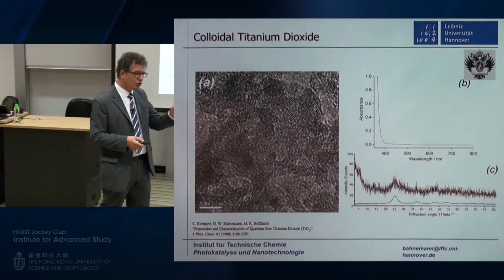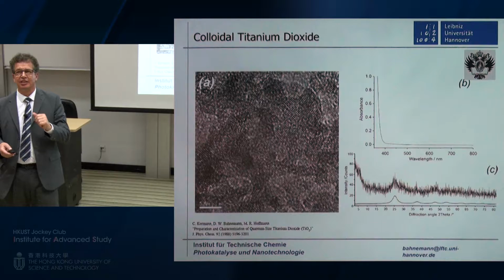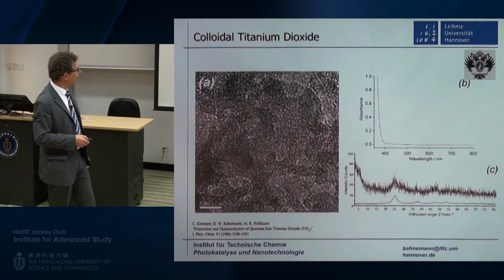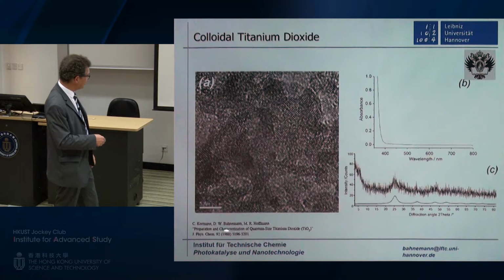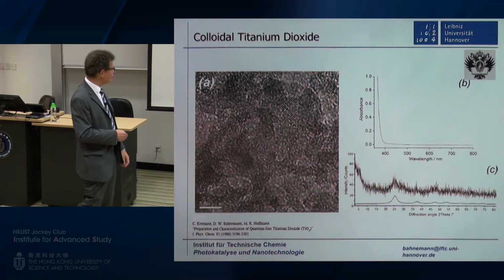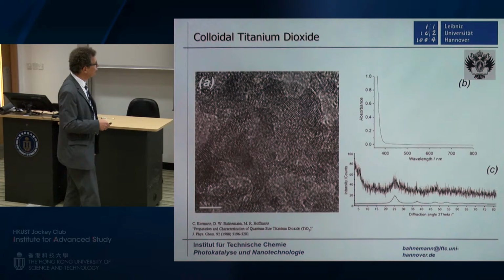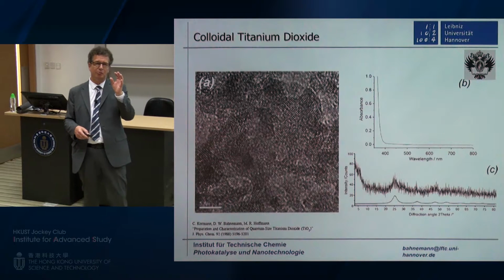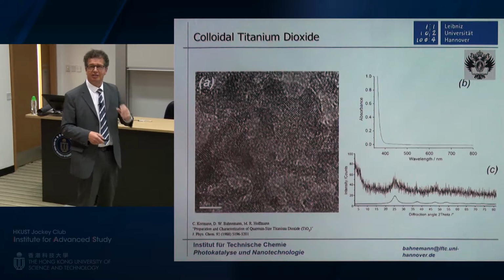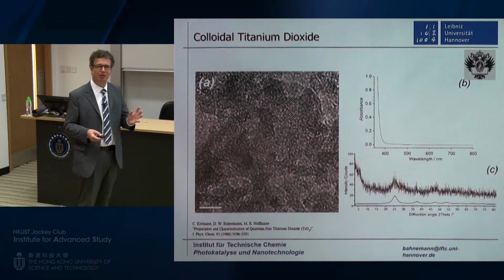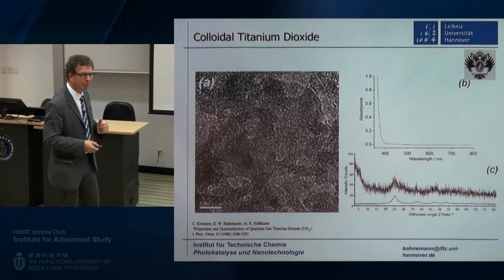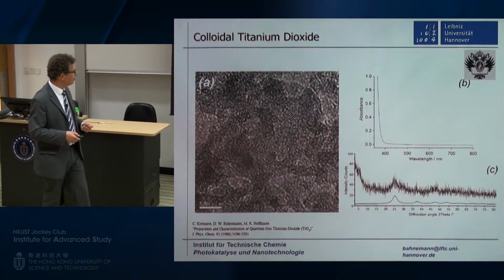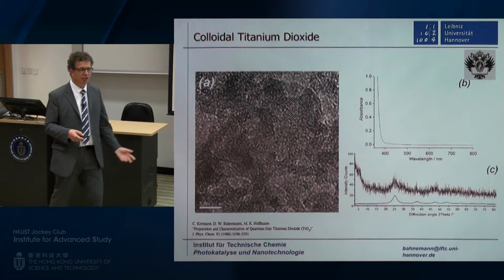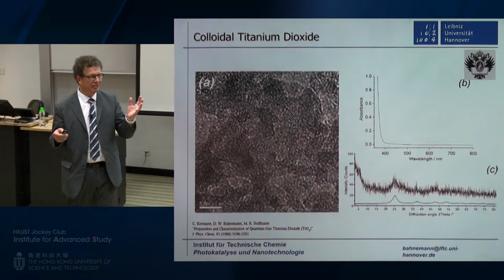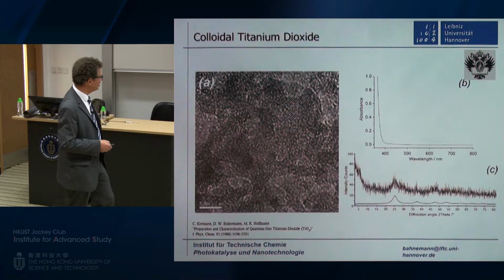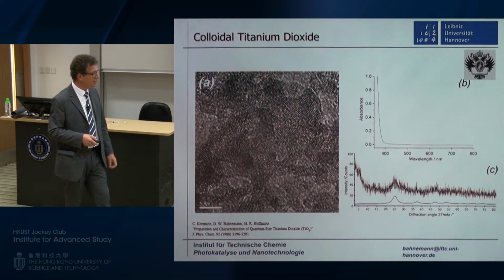Now let's switch gears and go to a photo process that is not only changing the system, but that is bringing about a chemical reaction. And we utilized some old material. When I was working at Caltech together with Michael Hoffman, we published a paper where we showed a very simple synthesis of titanium dioxide just using titanium tetrachloride as a precursor and water as the only reactant. I'm a physical chemist, and physical chemists don't know about very complicated synthesis, so I use this very simple synthesis here: titanium tetrachloride plus water, giving you TiO2 and HCl. Actually, the military uses this a lot. This is the smoke bomb used by the military a lot. That contains TiO2, which is not so harmful, and HCl, which is a little more harmful.